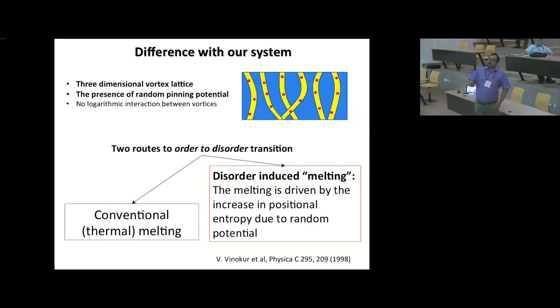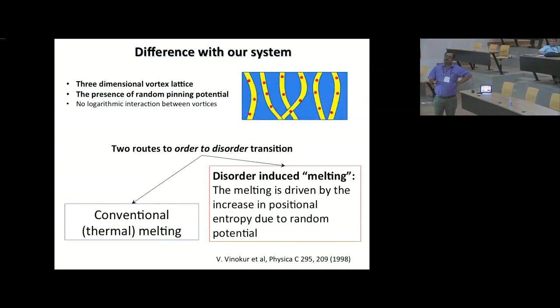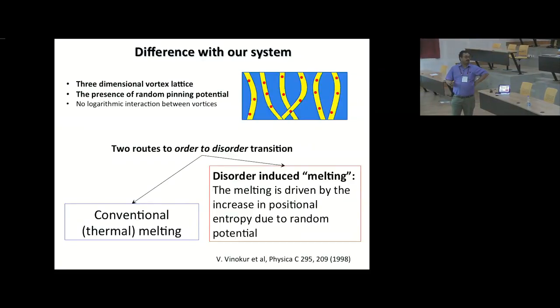Now, to look for an alternative, if we leave BKT aside, there are two routes to an order disorder transition. One is conventional melting, what we call thermal melting. But there could be another route, which is a disorder-induced melting. When I say melting, it's melting in a loose sense, an order disorder transition which is driven by the increase in positional entropy due to random pinning. This was proposed by Vinokur in a paper where he was mainly dealing with high TC materials.